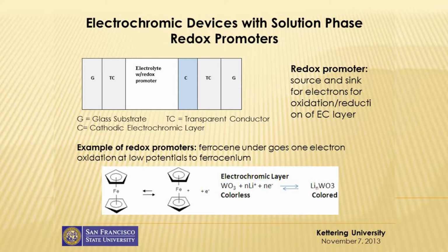Electrochromic devices with solution phase redox, and here is the typical structure: glass, transparent conducting, glass, transparent conducting. And this is the cathodic electrochromic layer. It uses only one electrochromic layer. And you have an electrolyte with a redox promoter in the sample. There are redox promoters, a source or sink for electrons for oxidation and reduction of the electrochromic layer. There are some redox promoters like ferrocene, which undergoes one electron oxidation at lower potential to another form, ferrocenium, as you've seen in here.